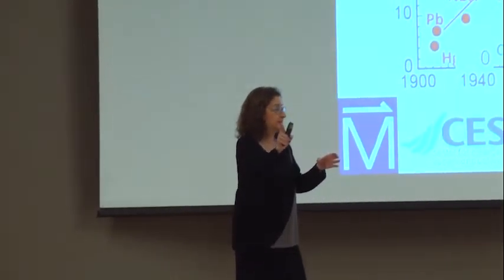If you look at the wave function orbitals, the wave function symmetry, do you have a prediction about, other than D-wave, what we should be looking for? No. All we know is the highest TC superconductor is D-wave, but in some sense that's quite detrimental to applications, because if you have any scattering within the material, you break pairs like crazy. And if it's an S-wave superconductor, you don't break pairs. Some of the work that we've done in the center is taking the iron-based superconductors and putting a lot of pinning centers in them, and finding that the TC is not going down much. So in some sense it's great for high TC, but it's terrible for high JC.